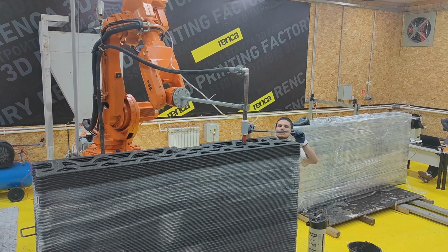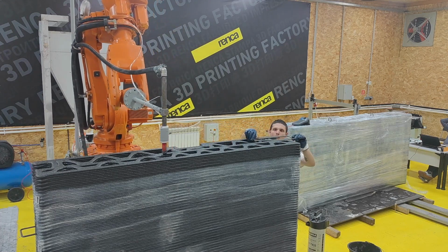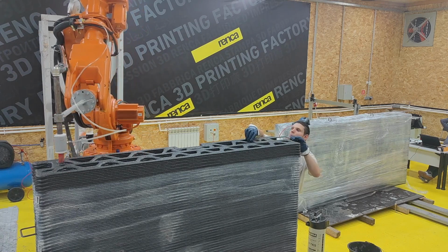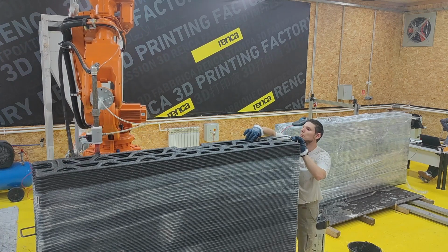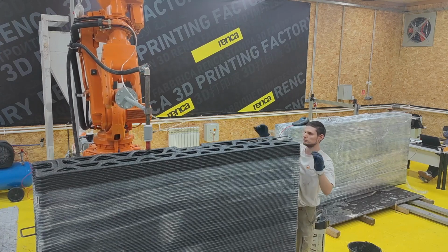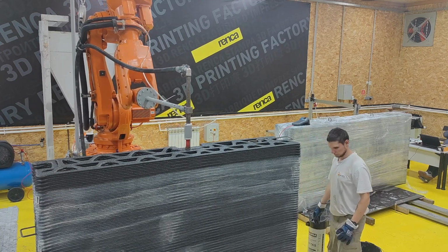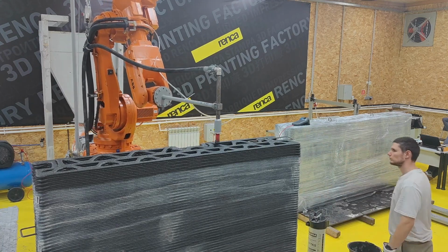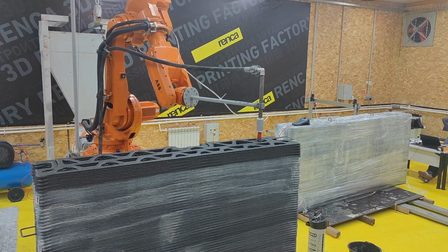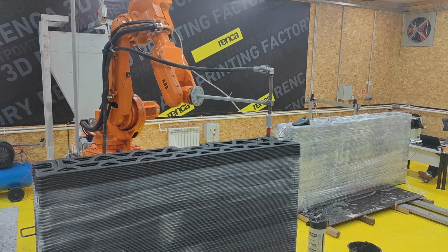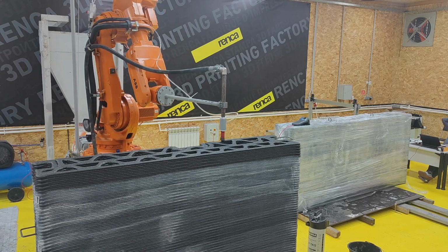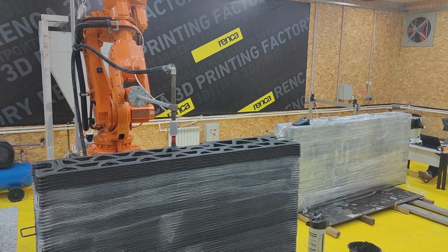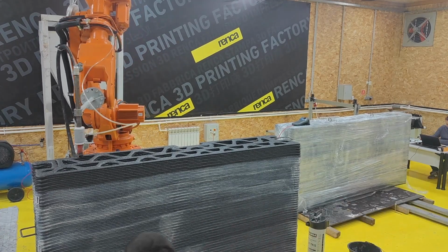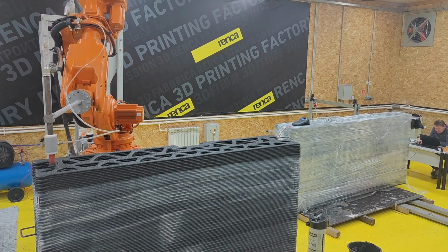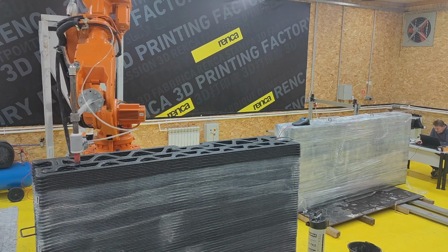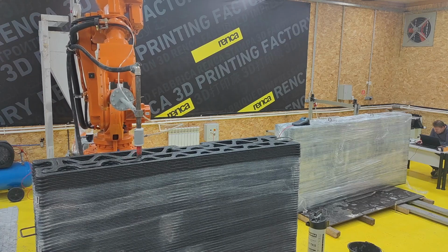But actually in Australia, there is a really good situation concerning application of geopolymers, because in Europe and mostly the United States, you have a standard for concrete where it is stated that you have to have at least a certain amount of Portland cement inside your concrete. In Australia, there is a performance-based standard that doesn't care what you put inside your concrete. When they meet the requirements, they have strength, they are freeze-thaw cycle resistant, water resistant, nobody cares what you put inside. And that's why in Australia, there is a good market for geopolymers.